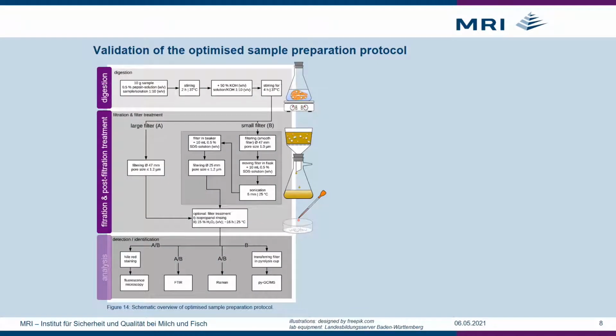The final sample preparation protocol is shown schematically on the left. First, the sample matrix is dissolved and then filtered with either one large filter in option A to be analyzed directly, or pre-filtered using a smooth filter in option B for pre-concentration of the particles, which are then rinsed off onto a small filter, for instance for the application of imaging techniques.